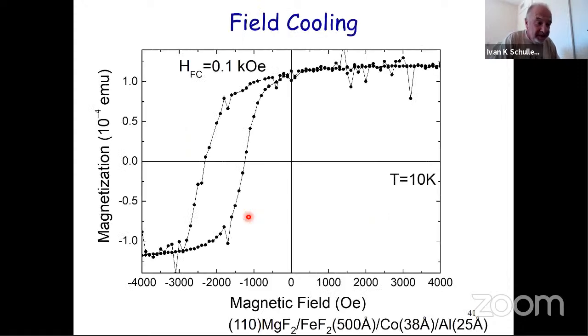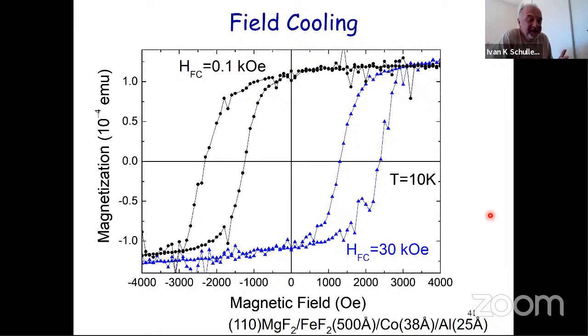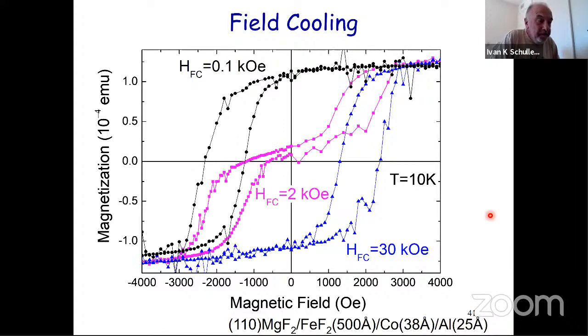Now, remember the way we do this experiment, we field cool below the Néel temperature, and the hysteresis loop goes to negative values. So there it is, the hysteresis loop of, let's say, iron fluoride. And it's shifted towards negative values. Now, let me cool it in a bigger field, which shouldn't do anything. And if I cool it in a bigger field, the hysteresis loop shifts towards the right. So it depends on the cooling field. It's not as simple as Meiklejohn and Bean thought. And in fact, if you cool it in an intermediate field, you have two hysteresis loops.